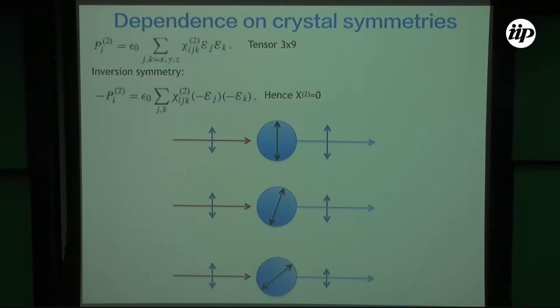And another property is that the intensity of the second harmonic that the crystal will generate will depend on how the incoming polarization of the laser is aligned with the crystal axis of your material. Of course this depends on this tensor, but for an easy case, if you have the incoming laser polarization aligned with the crystal axis, you're going to have a strong second harmonic emission. But if you misalign your crystal axis with the incoming polarization, you have a smaller second harmonic amplitude, and if you misalign more, it decreases. Okay, so you can use second harmonic generation also to probe the crystal orientation of your material. Okay, where are the crystallographic axes.